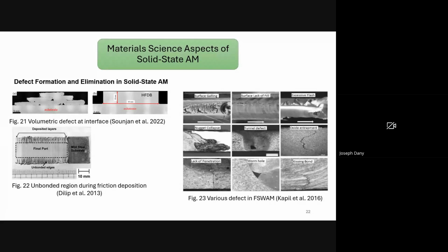These defects may appear below the surface or as surface tunnels. Then the lack of penetration, joint incomplete fusion along the thickness due to insufficient welding energy or improper tool placement. And kissing bond, a barely bonded interface often caused by oxide layers or insufficient stirring, where surfaces are in contact but metallurgical bonding is weak. It occurs if the tool stirring does not access key interface regions. And finally, wormholes, a type of tunnel defect with a narrow elongated void in the stir zone, which is often parameter dependent.